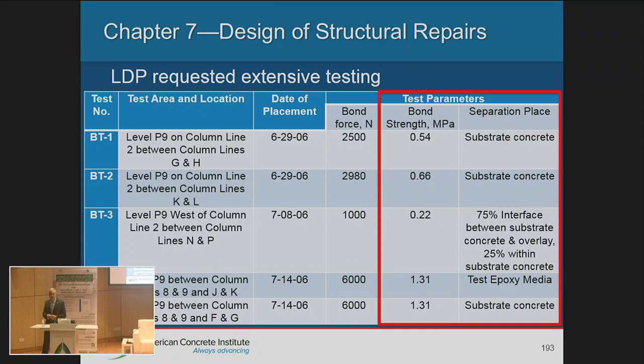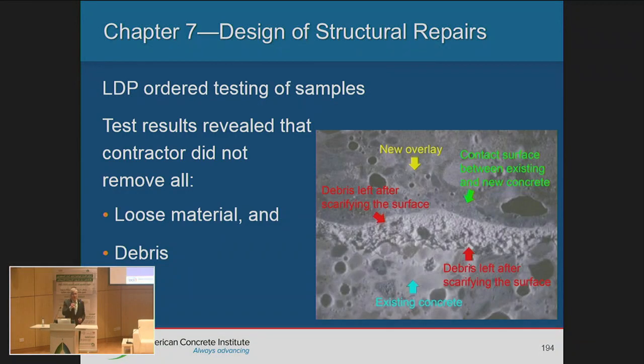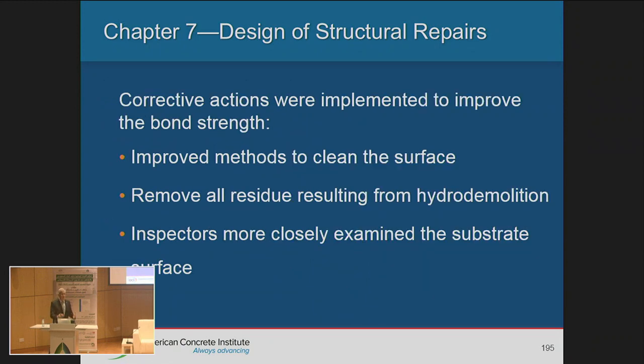So that was alarming. The engineer stopped the work and tried to figure out why they got such low test results. So they took a few cores to the petrographer to analyze them. And what did they find out? If you look at this picture, this is the existing concrete. This is the new concrete, the overlay. And what do we see here? They found debris. They found loose material, which created a debonding between the new and the existing. That means the contractor did not do a good job of cleaning the concrete after removing it. So the work was stopped, meetings were held, and the outcome was that the contractor needs to do a better job and needs more supervision.